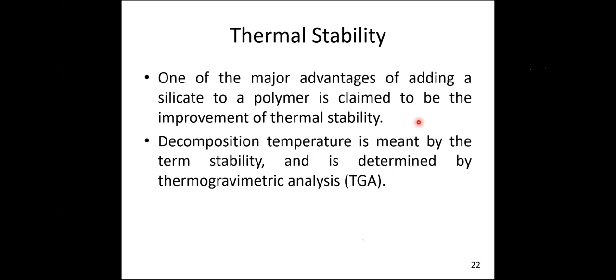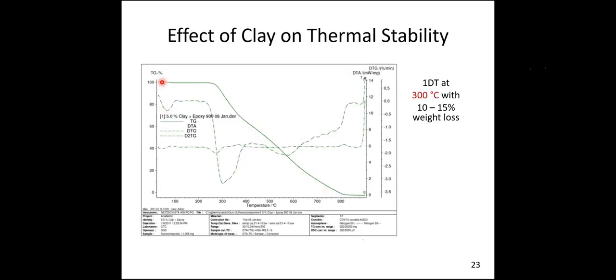Again, thermal stability is a very simple characterization test to understand the decomposition temperature of that epoxy. So we used thermogravimetric analysis for this study. If you see the green color, the left hand side shows the mass percentage. The x-axis shows the temperature. When I keep on heating the sample, around 300 there is a drop in that curve. That means it shows the weight loss, mass loss.